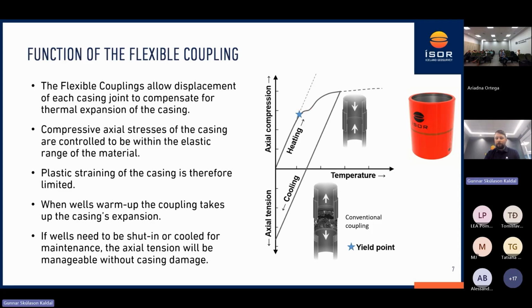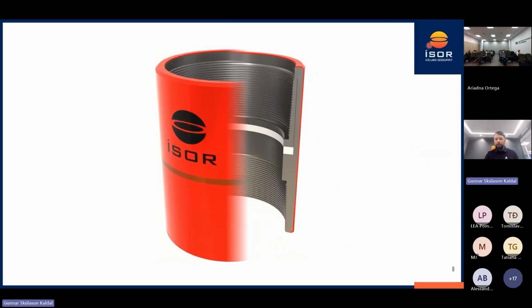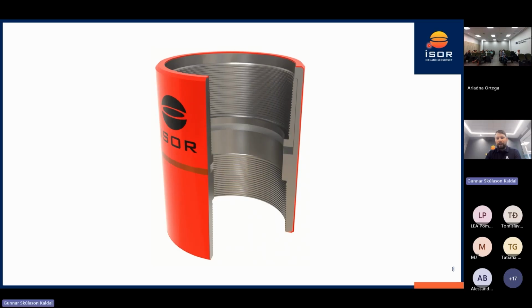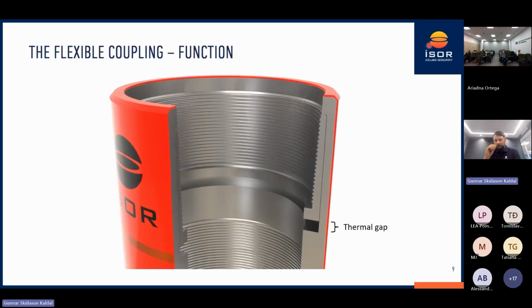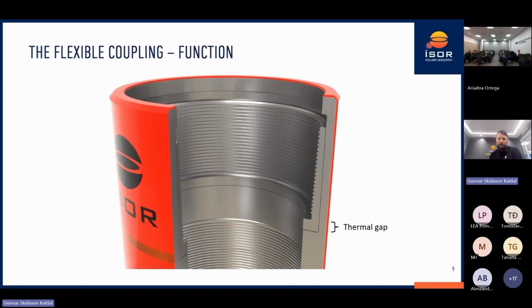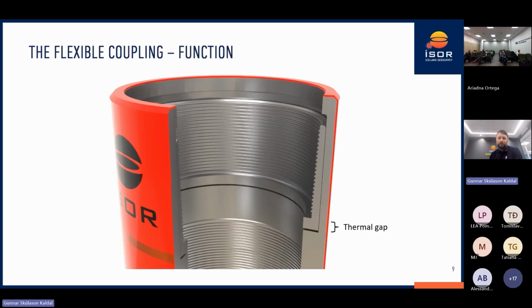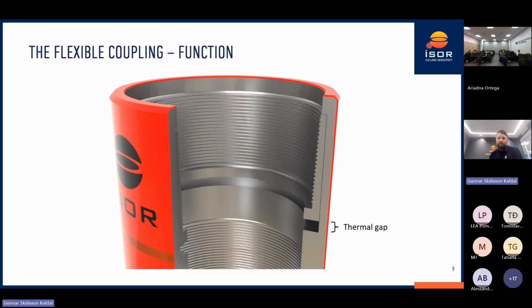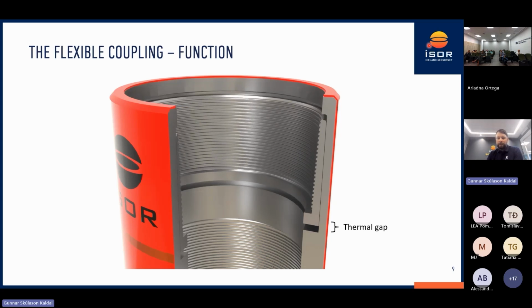So what we are doing with the flexible coupling is trying to work in the elastic range of the material, so we are not allowing the casing to get to these high stresses. If we look into the coupling, we can see there is a thermal gap, and this thermal gap closes down when the casing expands. So instead of creating these high forces, it allows each casing joint, about 12 meters, to expand. And if the well needs to be worked on and cooled or injected with drilling fluids, then it simply will open up again.